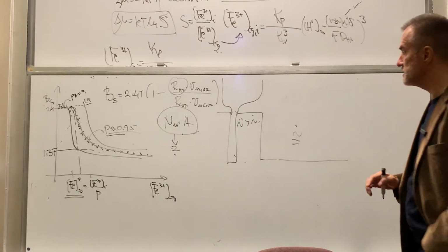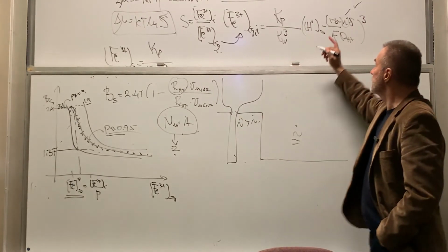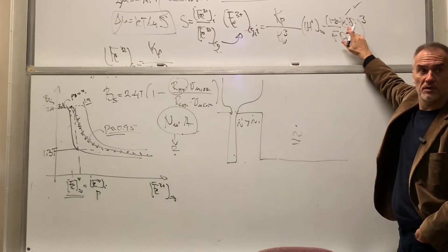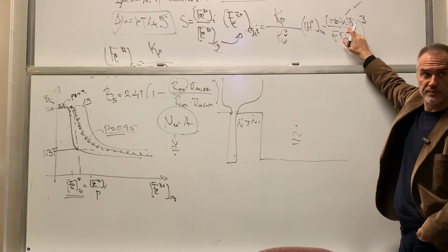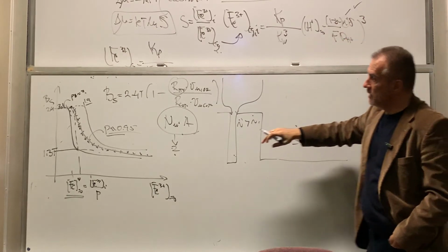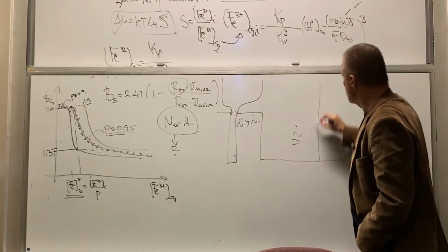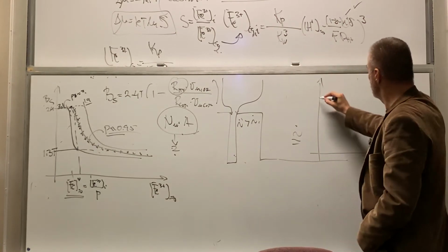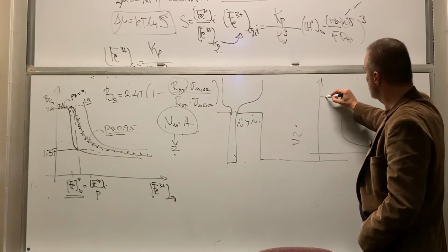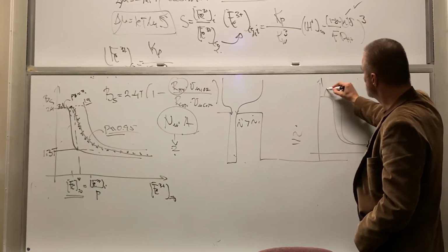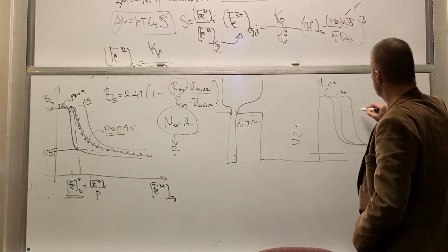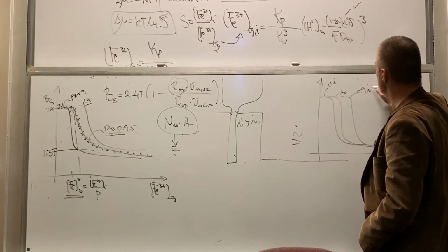Well, same thing. I can now have my model everything the same, but I can simulate the curve with a little bit higher current, 10% increase, and a little bit lower current. A little bit higher current, if this is your process, I naught, your higher current, which is 1.1 I naught, will be here, and this will be 0.9 I naught.